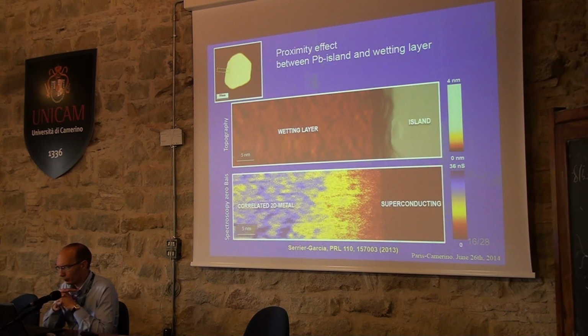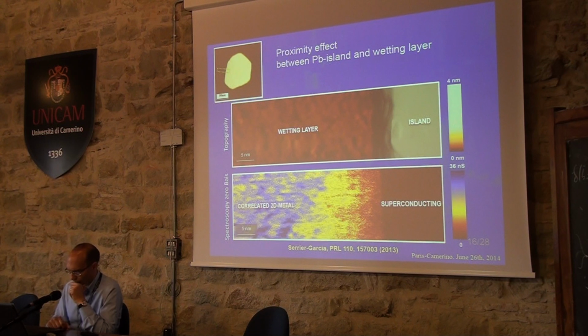This smooth decrease, as the bottom map shows, is not really uniform. You have the general trend of smoothing and reducing the proximity gap when you leave the superconductor for the correlated two-dimensional metal, but yet you still have some spatial fluctuations, which are very complex to account for.